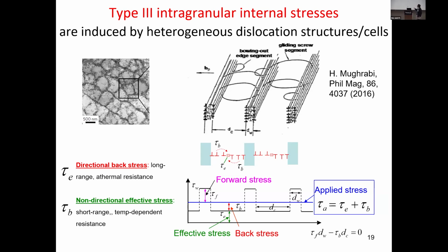We have the dislocation cell walls, as schematically shown here. They have high dislocation densities. You can consider them as a hard region, while within the cell interior we have low dislocation densities, and those are the soft region. So essentially, it's a composite with hard and soft phases. But more importantly, as you strain this composite, the deformation compatibility between hard and soft phases requires the generation of